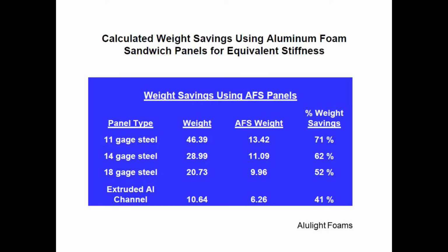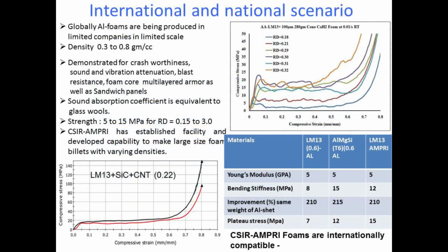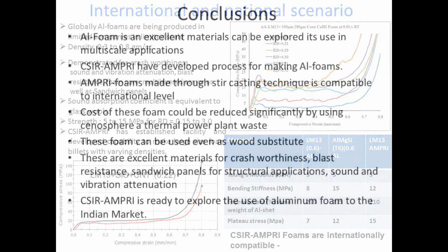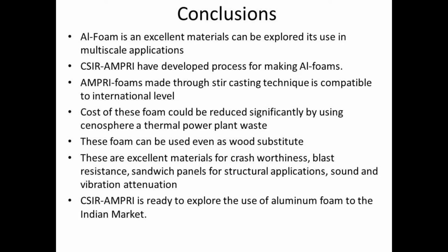And if you see the properties of our foam, it is comparable to the internationally available foam made by Alulight and Alporas. And this is the conclusion. We have developed our confidence for making aluminum foam at lab scale, and the technology is almost ready, and we can transfer the technology to industry. It does not need a huge amount of money to set up an industry. Around 5 to 6 crore is sufficient to make foam of around 500 to 600 kg per day.